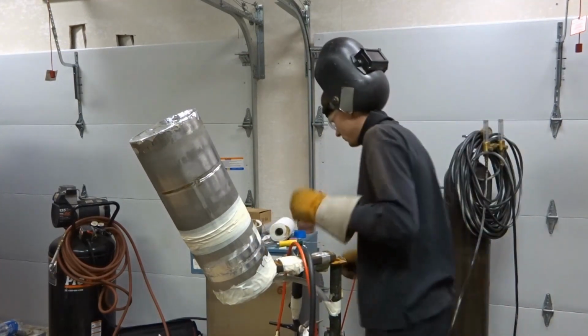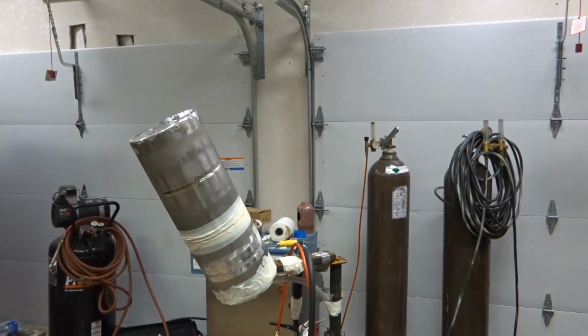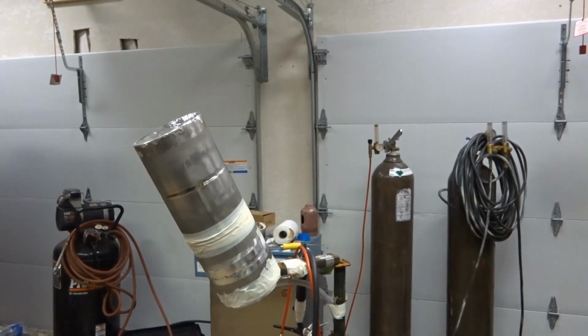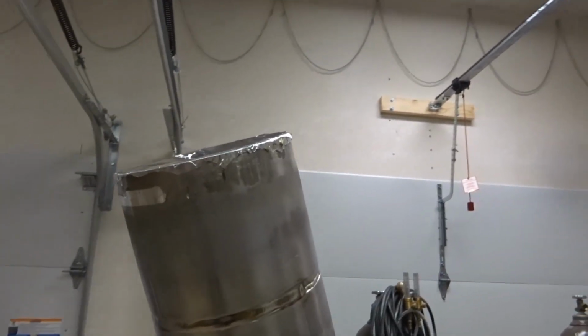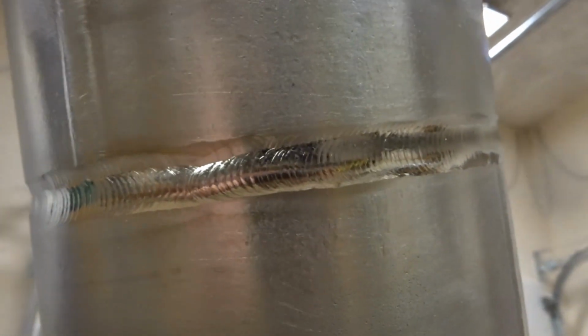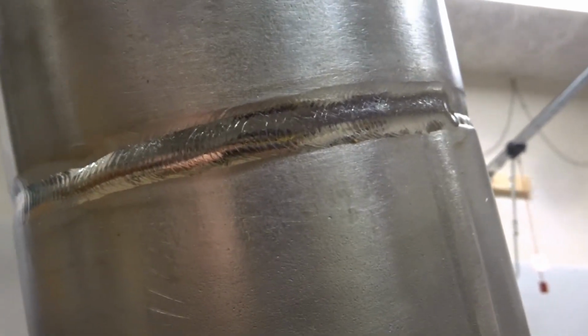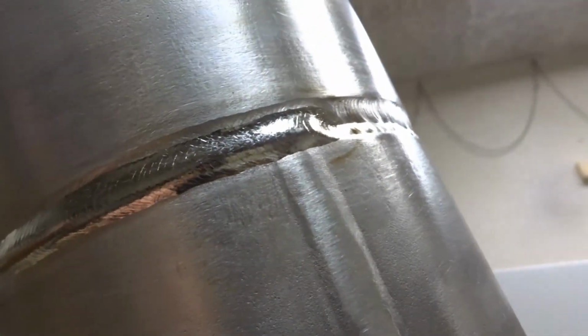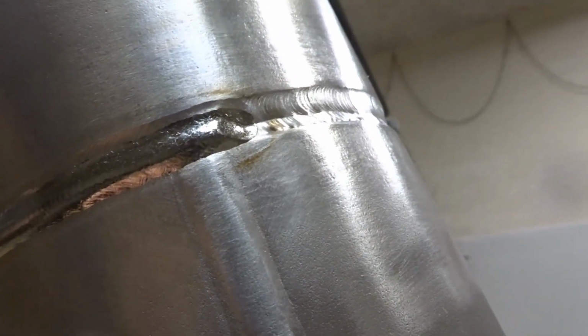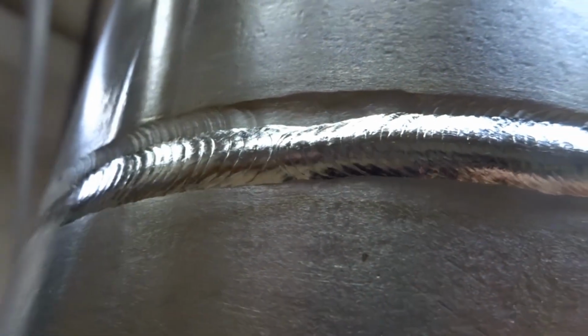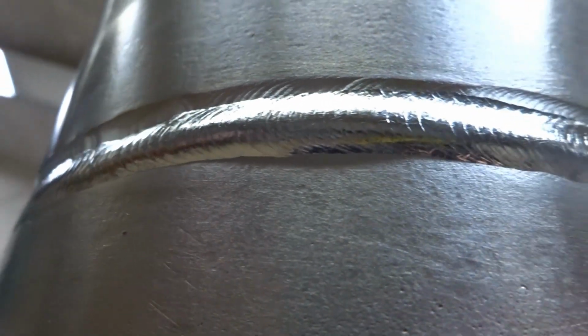Even the aluminum, you know, the aluminum is another metal, because you see, the aluminum has an oxide that melts at 3600-3700 degrees Fahrenheit. The metal underneath, the clean metal, when the oxide is removed, melts at about 1200 degrees Fahrenheit. I think it's about 660 degrees Celsius, whatever it is. Can't remember the conversion. But you see, if you're a very sloppy, very poor welder, with very poor welding technique, or just very sloppy in general, if you weld over the oxides, you'll for sure have porosity, lack of fusion. You'll have these certain things showing up in the weld, especially on X-ray. And even if you do a bend test, your coupons will just snap in half like a twig because you're very sloppy and you're not welding the metal how it should be welded.